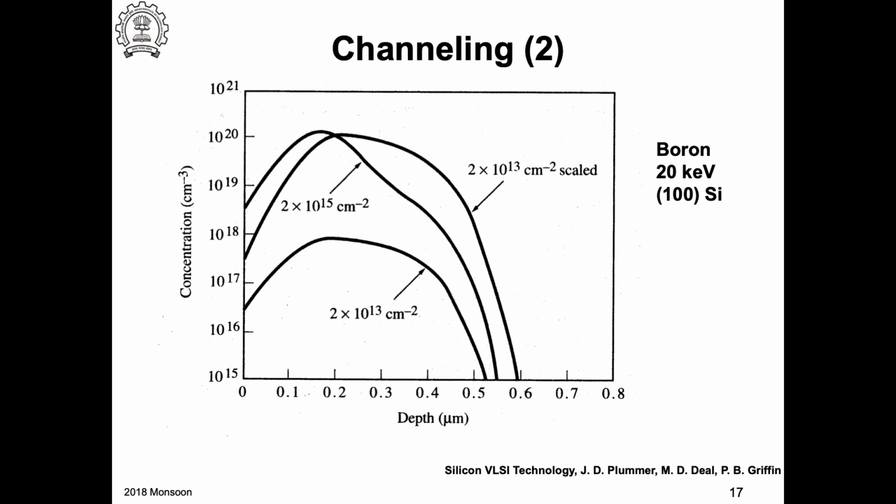So essentially, two distributions are used. Each one would have 4 moments, so this would actually be an 8-moment distribution. The dual Pearson model is used in simulations.